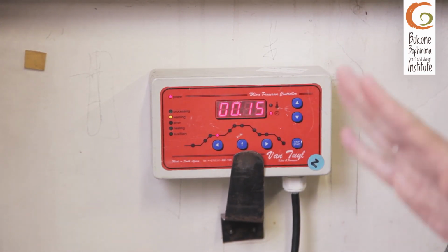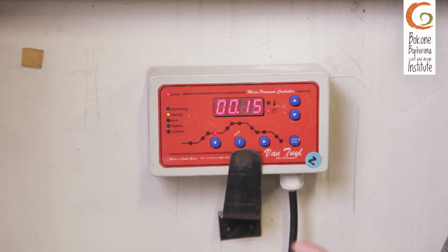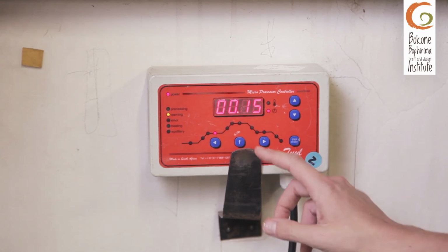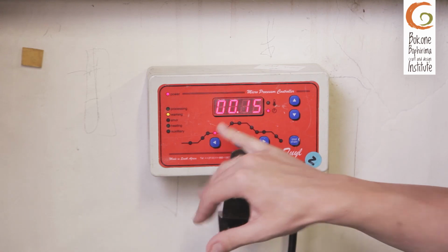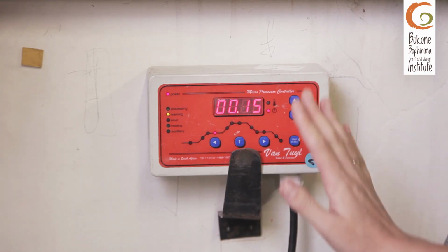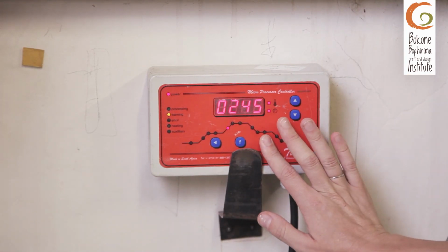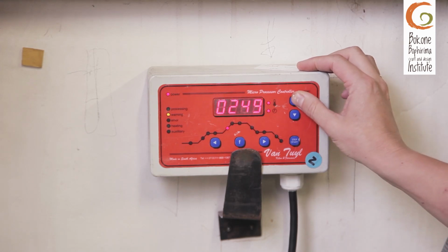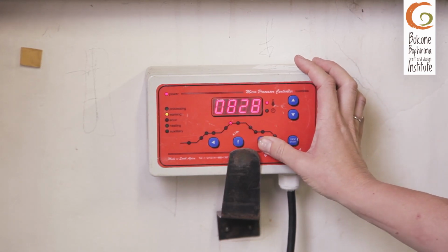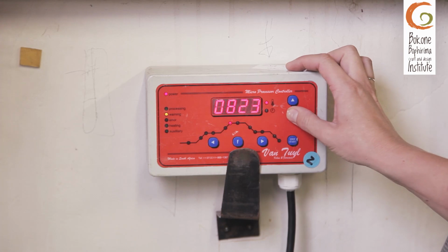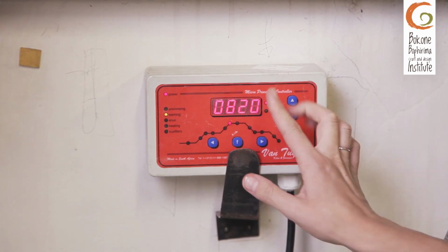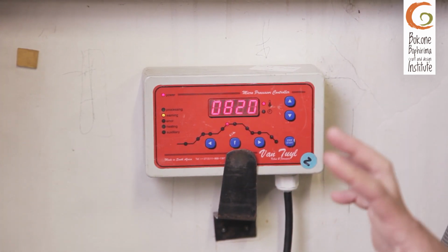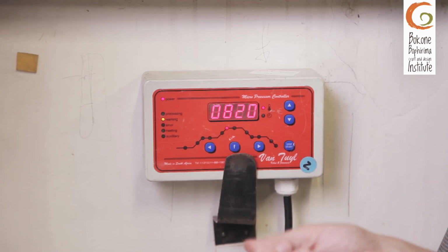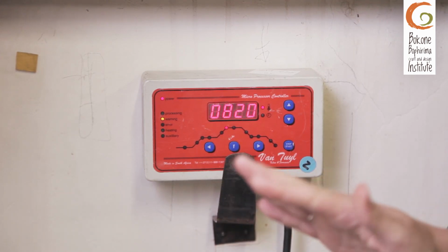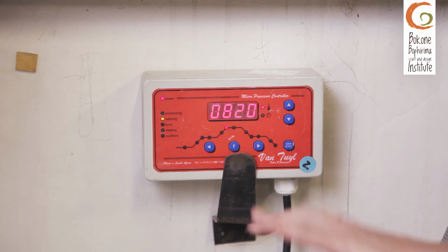Reason being because I've got two layers of glass and I want to ensure that my bottom painted layer is also at 580 before taking it up to its top temperature. I'm then going to take the glass up 250 degrees an hour up to my top temperature of 820 degrees. And at 820 degrees, my glass will become soft and the edges will fuse to become one on the surface. So it will not be seen as two layers of glass anymore.